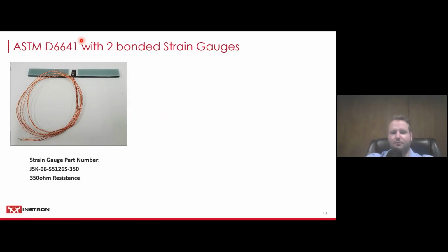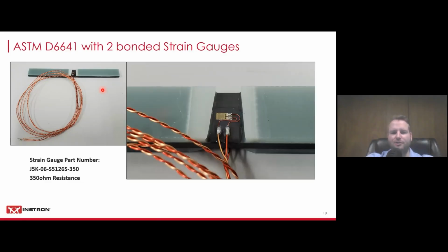You would run this test if you follow the standard and you determine the modulus and basically all the results that you need. You do have to use bonded strain gauges, which would look like this. You need to use them on both sides of the specimen. This is how that looks, and you get your lead cables here on the bottom coming out and here on the top.